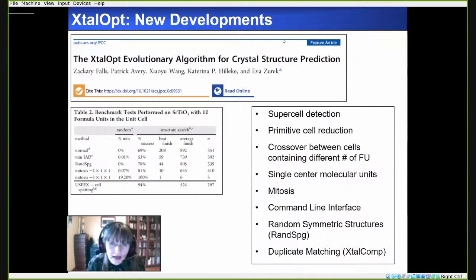XtalOpt has been recently developed. Here is a recent feature article where the developments have been summarized, so it can be used to study and predict the unit cells of much larger systems than was previously possible. I will not go into all of our recent developments. Here I just show recent benchmarks that were carried out on a supercell of strontium titanate. So this has, I believe, 50 atoms in the unit cell. Whereas in previous tests, the first version of XtalOpt was unable to reliably find the global minimum structure, we can see that our new techniques are able to find the global minimum structure with up to 100% success rate using, for example, this mitosis or cell splitting technique.